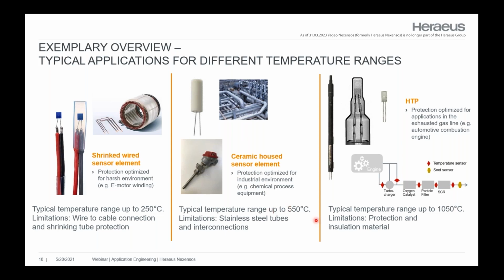If it comes to temperature ranges up to 1000 degrees, which are typically for combustion engines in our automotive world, then we have to work with completely different materials. That means we have different housing materials, which are high nickel based alloys. They have to be very well sealed with very special welding processes, so that everything is really nicely connected. And if you have these connecting wires here, they are protected in the tube with the mineral insulation, which is really special to handle. But this is the only chance to withstand 1000 degrees, with a good enough electrical insulation.